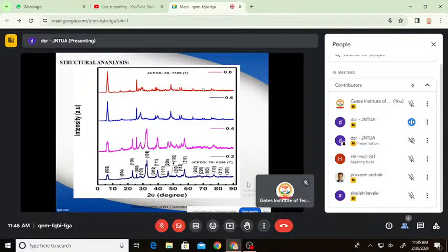Here we have varied the lanthanum content from 0.2 to 0.8 with respect to the variation of lead content, and all the planes are found to be in good agreement with the standard tetragonal phases of lead titanate and cobalt lanthanum titanate.